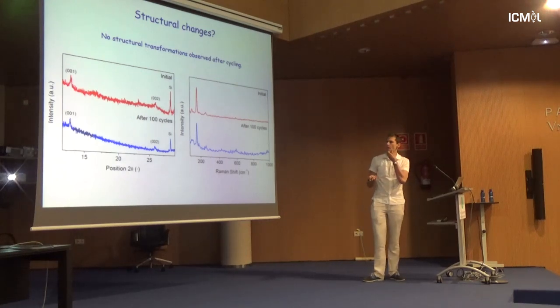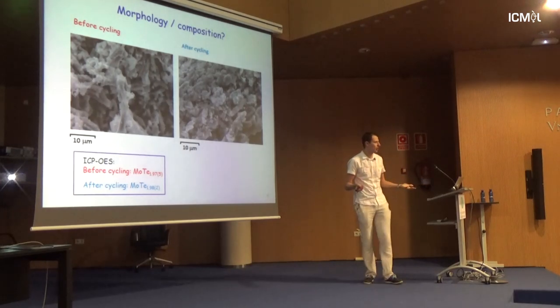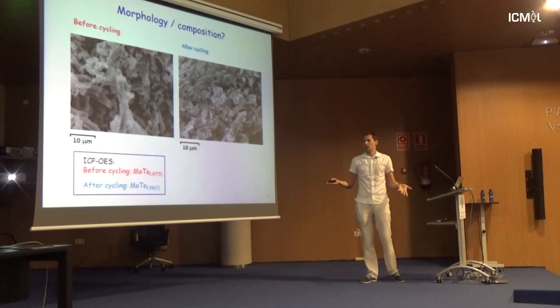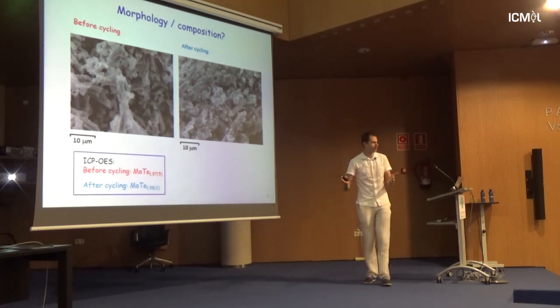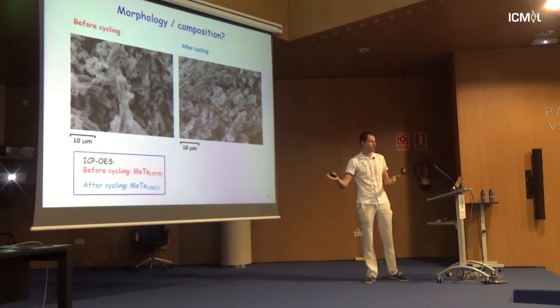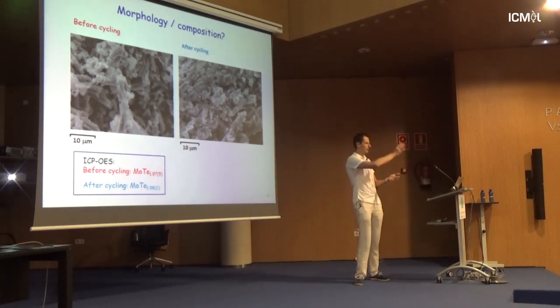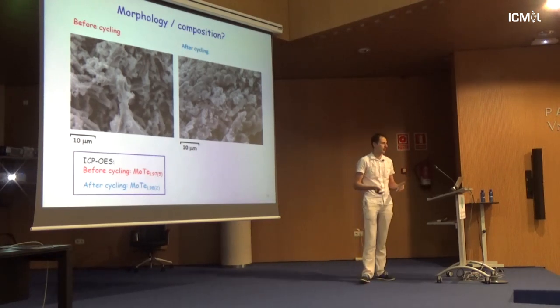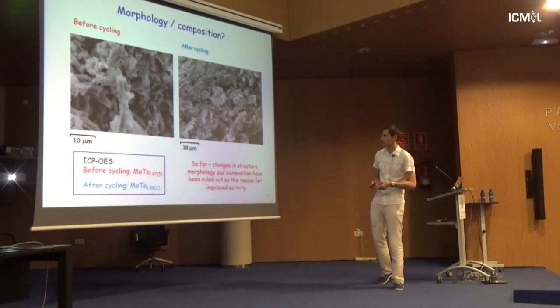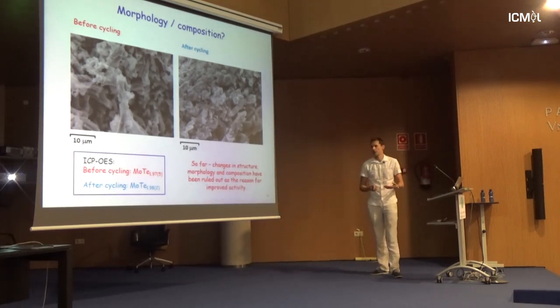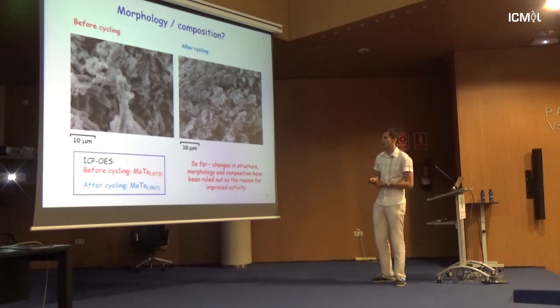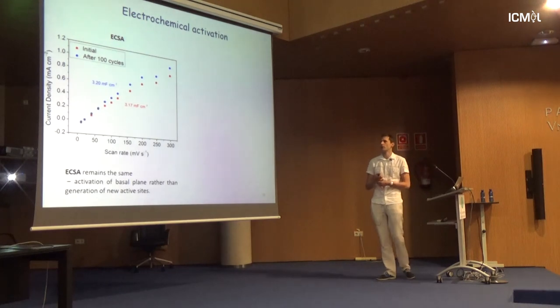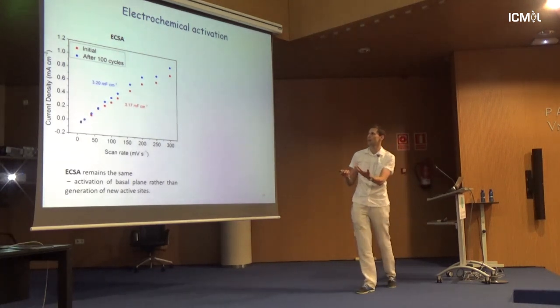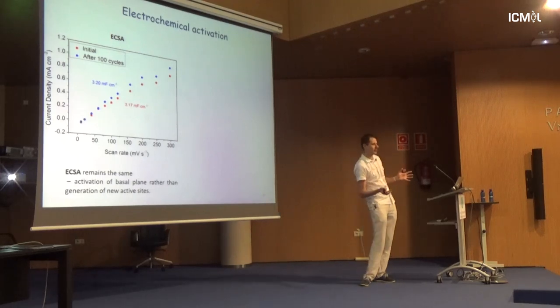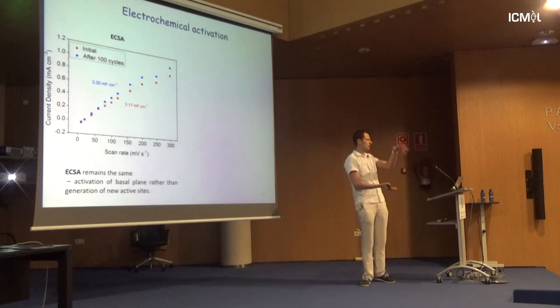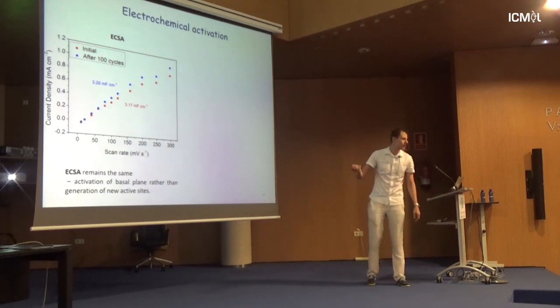So when we look, maybe there's some morphology change. Morphology is the same. But it was already quite clear because it reversed back, because if you had morphology change or composition change, it wouldn't come back. So it was quite clear for us there was some very unusual electronic effect. So no changes in structure, no changes in morphology, no changes in composition. So what could it be? So we tried also to look at the so-called electrochemical surface area. Maybe we have some surface area change, maybe the materials start breathing. And again, they're just identical, they're just the same.